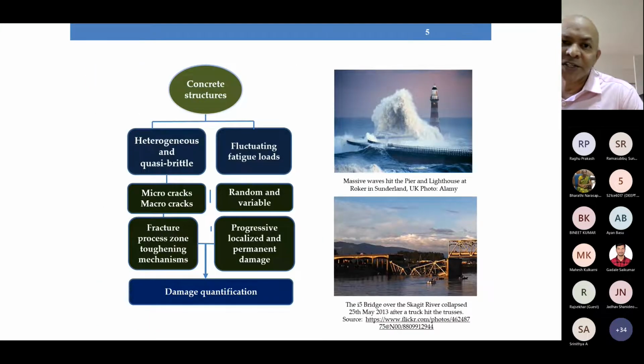When we come to concrete structures, as I told you, the concrete is heterogeneous, quasi-brittle. A lot of micro cracking takes place in the fracture process zone. A lot of toughening mechanisms occur. But also, when you look at the loads which act on this structure, very seldom do we have a concrete structure wherein we have simply a monotonic or a static load. Most of the time, concrete structures are subjected to fluctuating loads known as fatigue loads, which are random in nature, and this fatigue leads to progressive, localized, and permanent damage in the material. So because of this permanent damage, it is a very good material for applying the principles of thermodynamics, especially the principles of irreversible thermodynamics to explain the process of damage in the material.